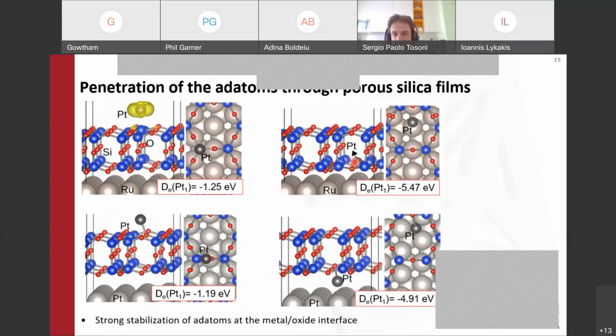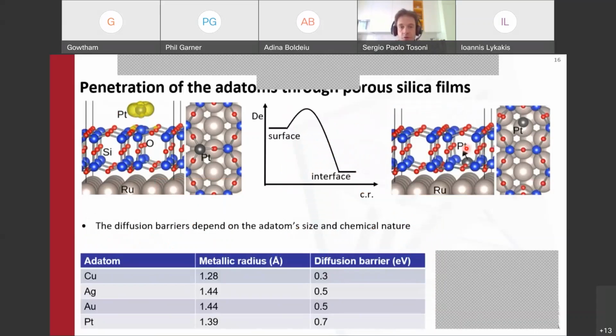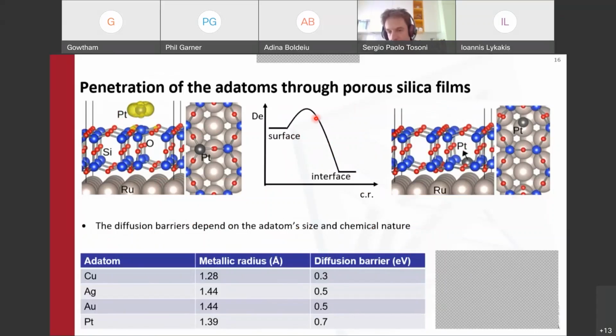Like in this case, platinum is stabilized here at the bottom layer of the silica film, while on platinum it goes even more down and strongly interacts with the platinum substrate. And as you can see, the increase in binding energy is striking. So the adsorption above the film is metastable with respect to the platinum atom coordinated at the metal oxide interface. But we have to consider that the process of diffusion through the film is an activated process. There will be a kinetic barrier to be overcome due to the penetration of the atom through the oxide film.